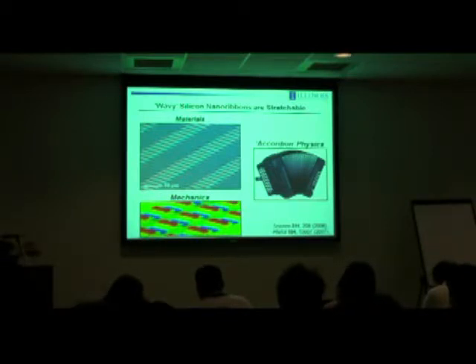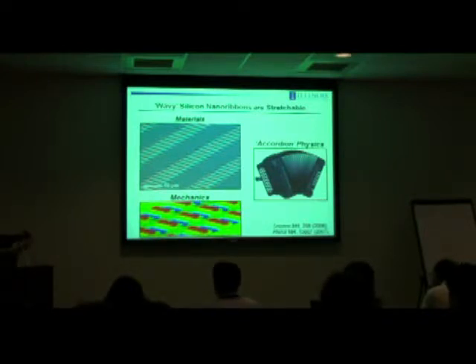So the way this works, you actually stretch the rubber substrate out a little bit. Then you deliver to its surface these thin strips of silicon. It bonds through interface chemistry that you define explicitly. And then when you allow the rubber to snap back to its original dimension, it puts these ribbons into a state of compressive stress. And the way that the material responds to that compressive stress is through a nonlinear buckling instability that spontaneously yields this kind of wavy silicon.